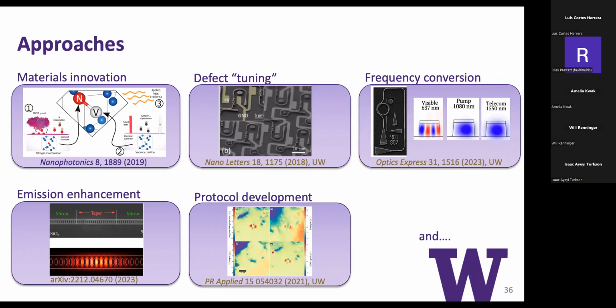like a protocol that's more robust to inhomogeneities, for example. One of my favorite ones is frequency conversion, which is, so someone mentioned or asked a question and said, well, so all we have to do is get rid of the inhomogeneity. That's true. But you don't actually have to make the defects identical. If you do frequency conversion of the two photons and convert them both to the same system frequency, you can do the interference at that converted frequency. And that will work. And so frequency conversion is a spectacular tool if it can be made to work efficiently and scalably for these systems, because it does two things: puts you at a frequency you want to work with, for example, telecom, as well as has the ability to erase which defect actually emitted the photon. It can be a very powerful tool, again, if people can get this to work efficiently enough.